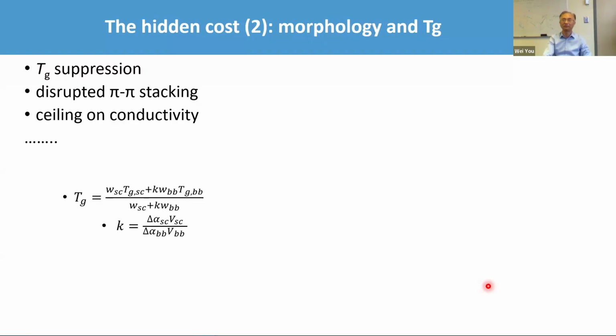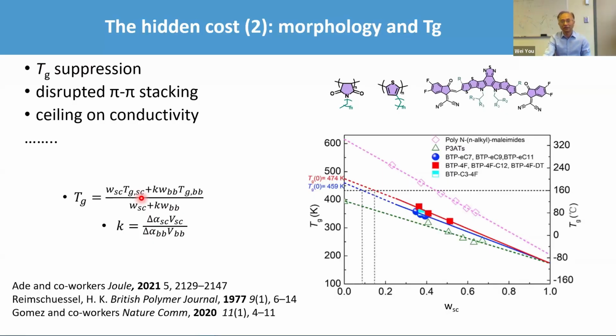So I want to spend some 10 seconds on Tg. This is the Gordon-Taylor equation. If you are in the polymer field, you possibly understand this particular equation pretty well. Essentially, a weighted fraction of the conjugate backbone and also the side chain. Harold Ade and Enrique Gomez and a few others have done very nice work to illustrate the point that having side chains will reduce your glass transition temperature. So let's take a look at this particular figure, which I took from one of the papers cited here. This is the weight fraction of the side chain.